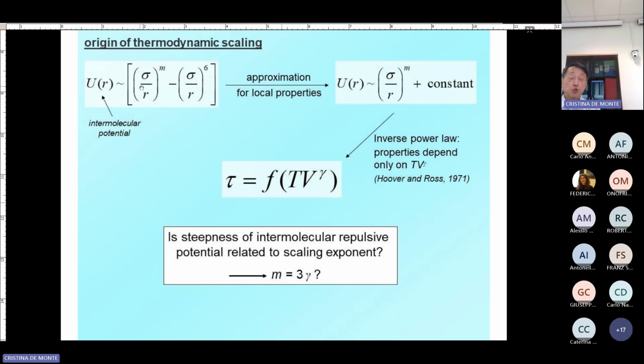And that is due to the fact that when you have a potential which is purely inverse power law, repulsive, from statistical mechanics, as proven in this paper for example, the relaxation time should have a functional form with dependence on TV gamma. This is a rigorous result. But in reality, even in van der Waals molecular liquids, it's not purely repulsive. You have the other term, the attractive term. That's why the Lennard-Jones is a 12-6 potential.